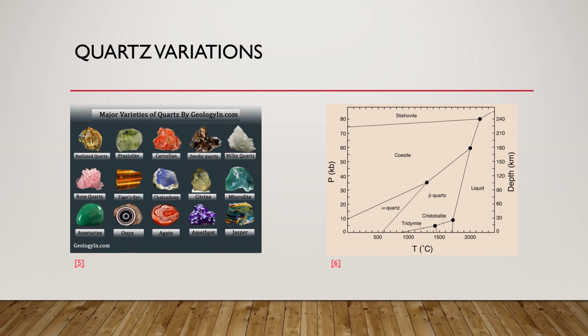Beta quartz may be either left or right-handed, and its C-axis is one of six-fold symmetry rather than threefold. High quartz can form directly from silicate magma or from high-temperature gases or solutions. It inevitably undergoes a transition to alpha quartz on cooling. The reverse is also true, as alpha quartz is heated to form beta quartz. The transition involves displacement of linkage between the tetrahedrons. Therefore, no bonds are broken.